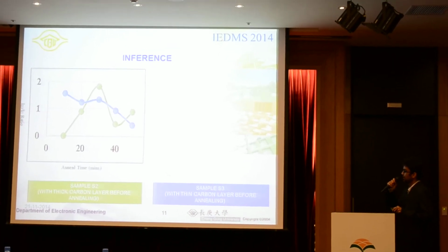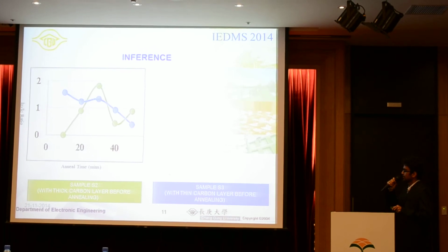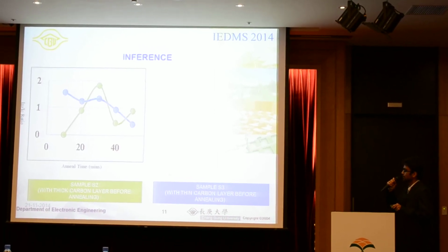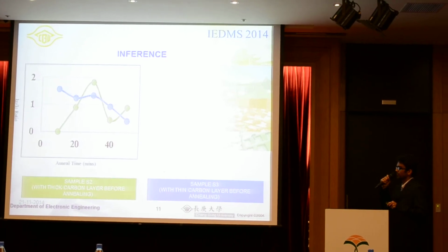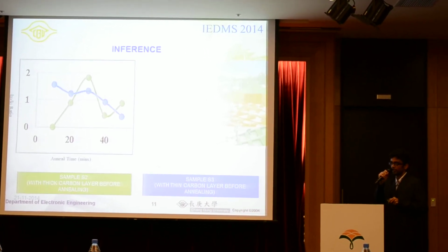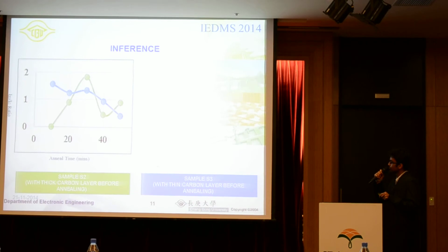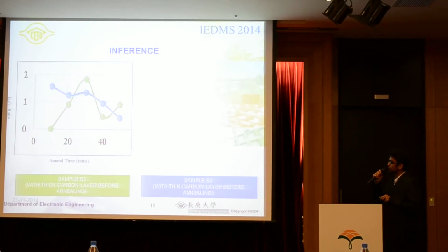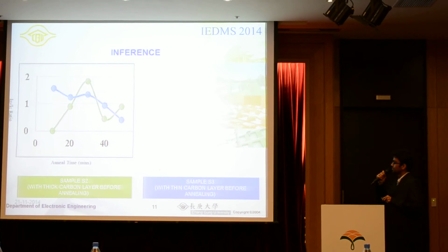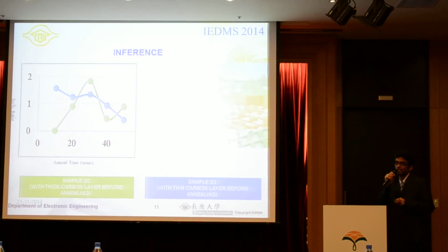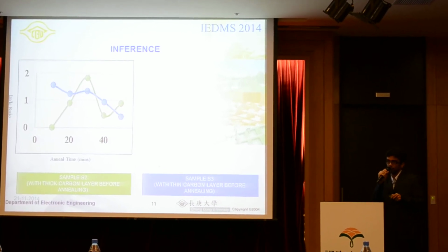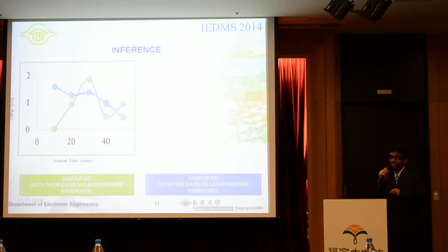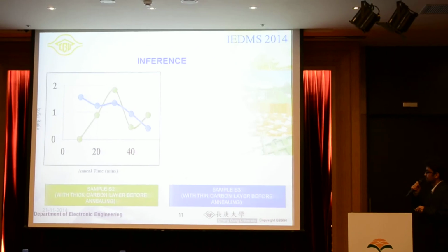So what happens is that slowly this carbon is trying to convert into graphene because of hydrogen interaction, and then at this point we have the maximum quality graphene. Then there's a drastic decrease because all the graphene formed here is etched out by the hydrogen present. Hydrogen has a dual role: it not only helps carbon form carbon species for graphene deposition, but it also etches out graphene. So it's a counterbalance situation.